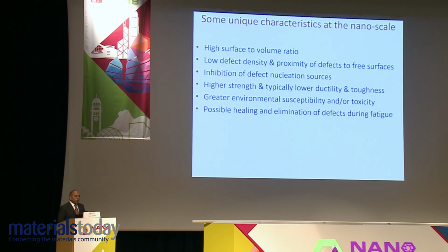We showed a few years ago that if you take single crystals of, say, a single crystal of aluminum, the mere act of mechanically cycling it at room temperature so that you impose a stress that's large enough to unpin dislocations and move them close enough to the surface so that the image forces can attract them and take them out of the system, but not large enough to create new additional dislocations, can lead to healing of the material, which is essentially a beneficial fatigue effect due to cyclic loading. Elimination of defects due to mechanical loading in certain nanosystems under certain conditions.